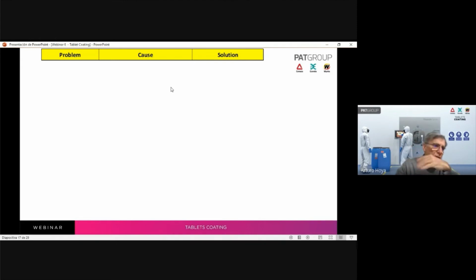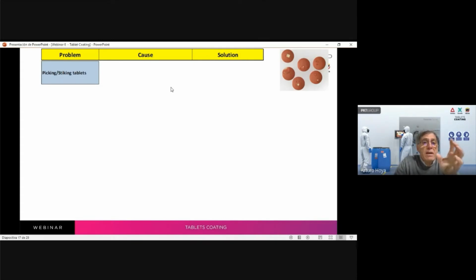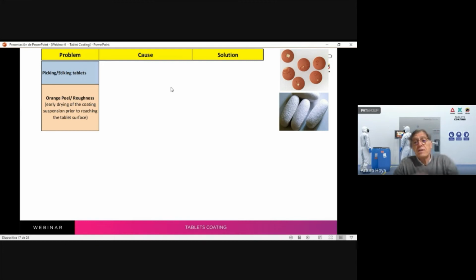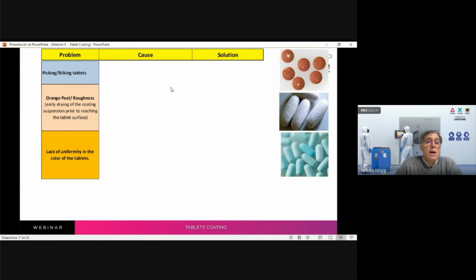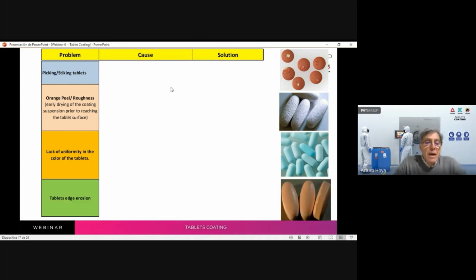The problem is very, very extensive, and we don't want to overwhelm you with information, but just some of the typical problems. Of course, the typical ones are, for example, picking and sticking of tablets. You have a typical picture on the right. These are picking. The orange peel, or roughness, where the surface is like an orange peel. The lack of uniformity in the color of a tablet, with a little more blue here, this is not good. And tablet edge erosion are other problems. Again, other problems exist, but these are very common.